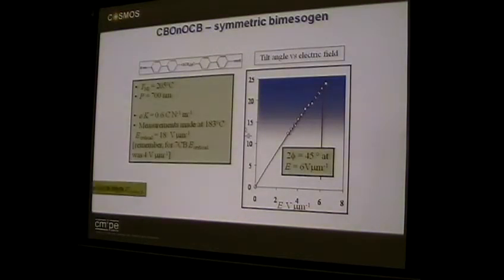So take one of our early materials. Say, okay, cyanobiphenyls are the basis, or were the basis of most liquid crystal displays. Take 2 of those and join them end to end. You have a bimesogen, 1 liquid crystal, 2 liquid crystals. Do you see a flexo-electro-optic effect? Yes, you do. There's the tilt angle, 0 to 25 degrees, at very low fields, 0 to about 6 volts per micron.